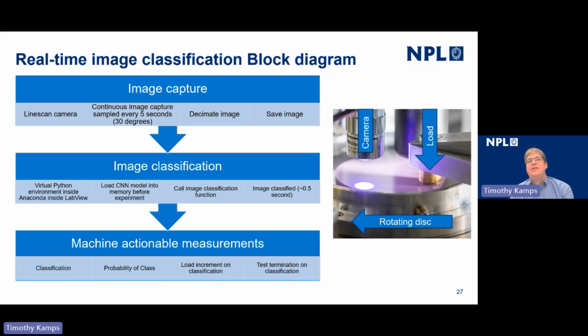And that then allows us to make machine actionable measurements. So the model returns the classification of the wear mechanism. It returns the probability that the image has been classified in that class. And then it allows us to make a couple of actions based on that classification. So, for example, we can run a load ramp test until we see the transition between 2 wear mechanisms, in this case between abrasion and adhesion.